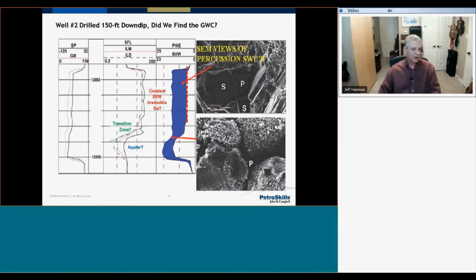Okay, so a second well was drilled because we had a discovery well. The bottom part of that reservoir was pretty certainly gas, hydrocarbon. We don't have a density neutron available to see if we see any sort of gas effects. The second well was drilled 150 feet down dip, and you can see a lower resistivity section at the very base. You can see once again the cleanest gamma ray, the maximum negative SP deflection. You can see again a resistive profile and the highest porosity.